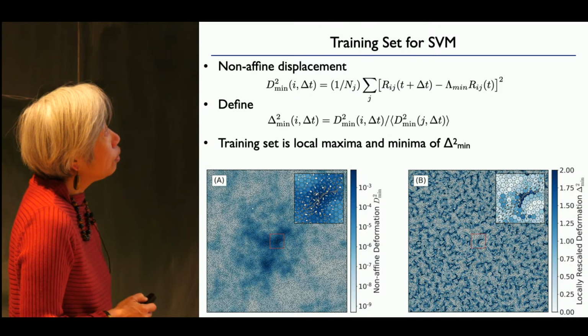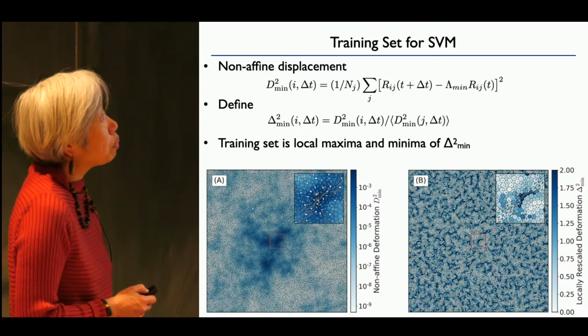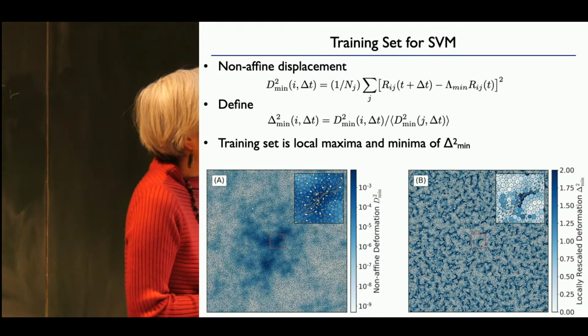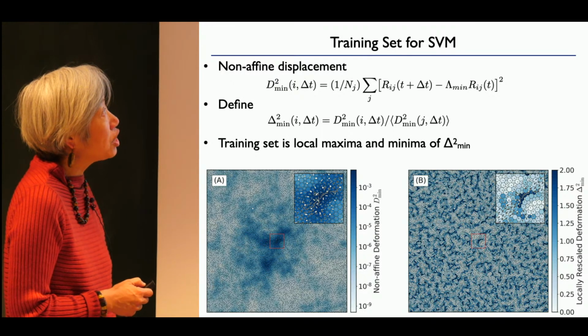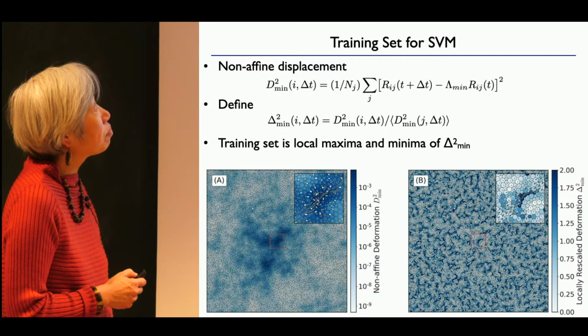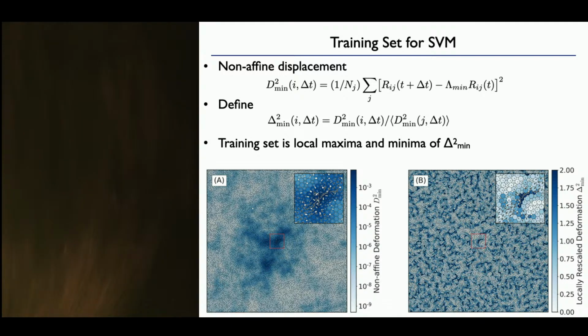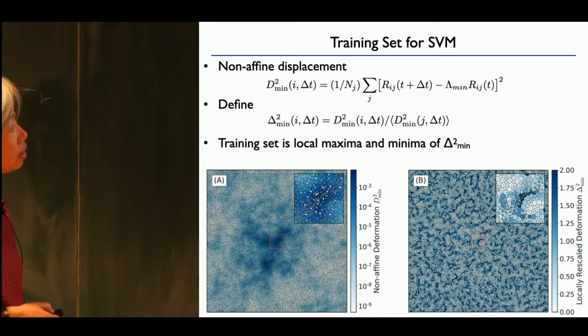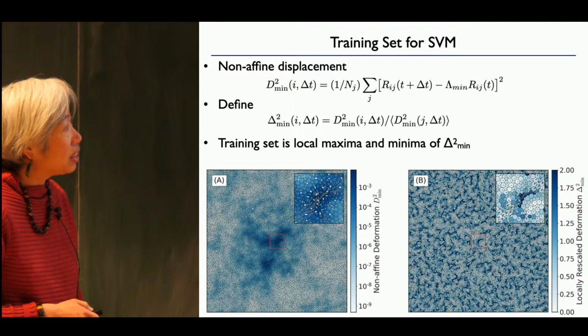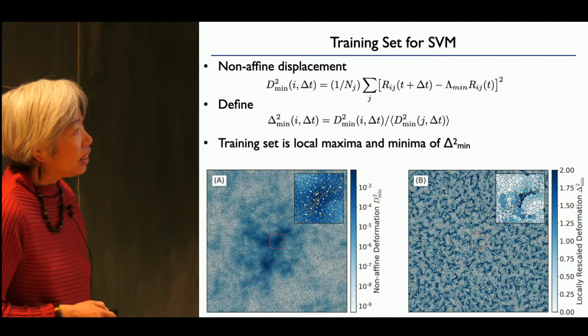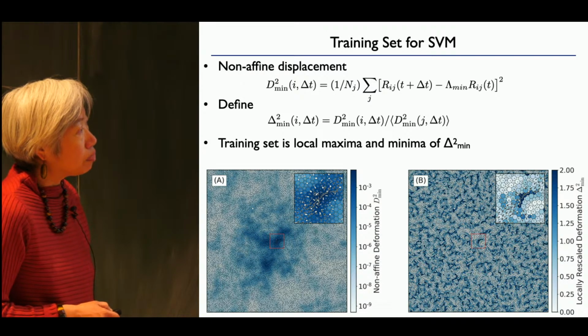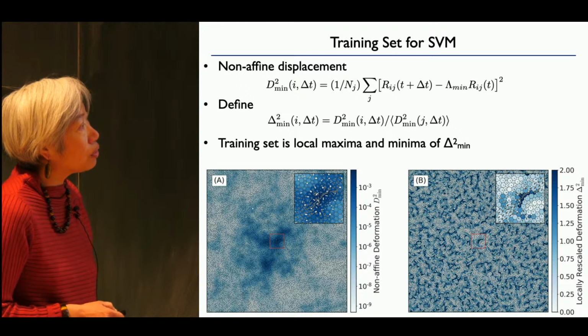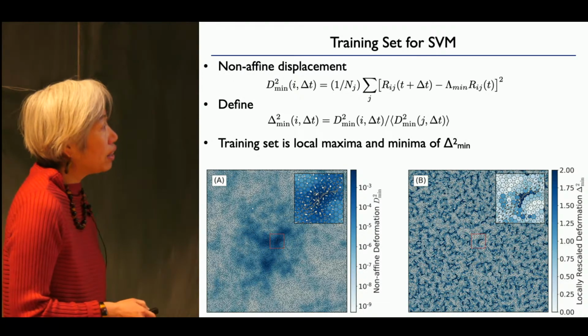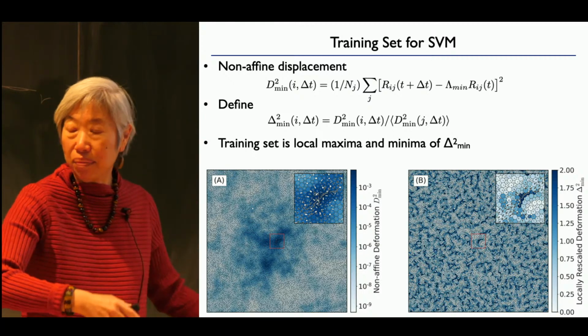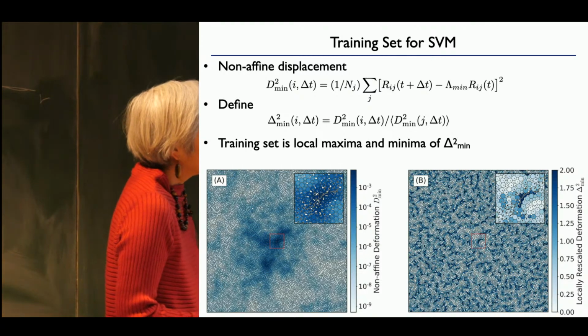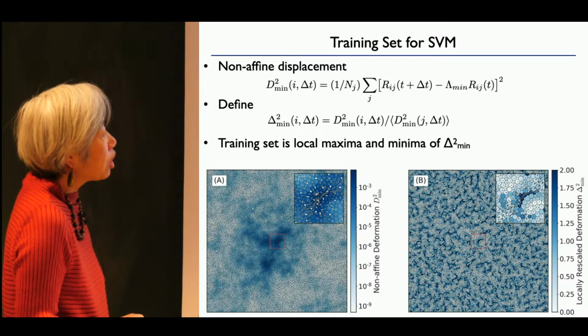You know, we started out training on the non-affine displacement of each particle. So we fit the neighborhood of each particle to the best strain tensor, look at the squared deviation from that, per neighbor particle. But this turns out, if you look at the mode that goes unstable right at the stress drop, you see that there's some particles rearranging here, but there's this very large corona of large values of the non-affine displacement that emanates from this, and that's expected because this is an elastic system, right? So you don't want to just concentrate on this.